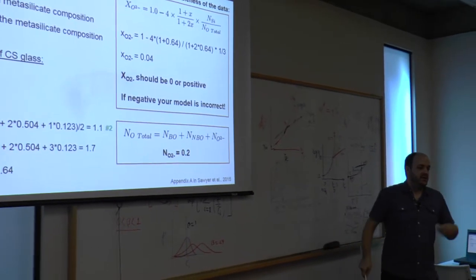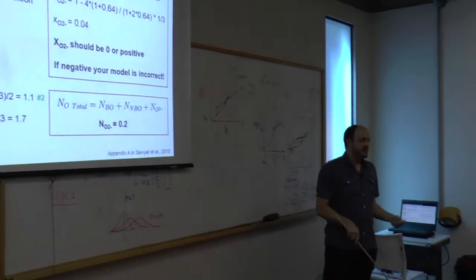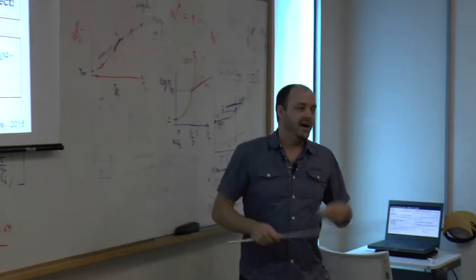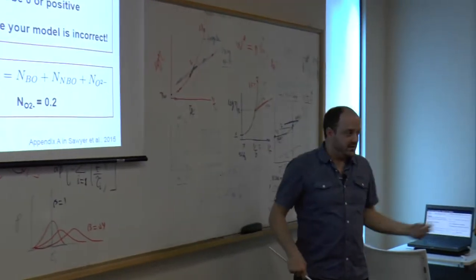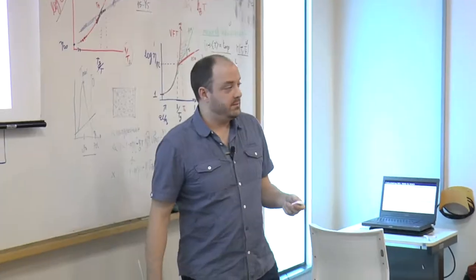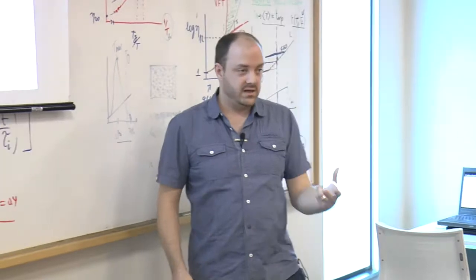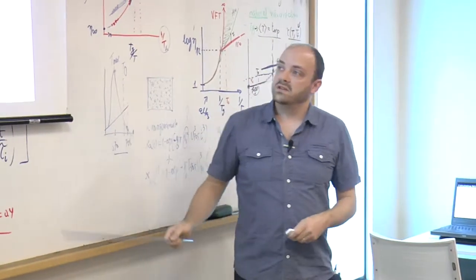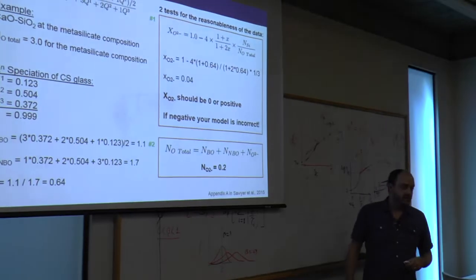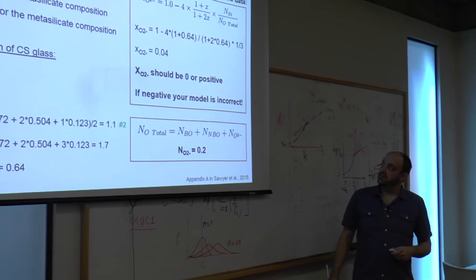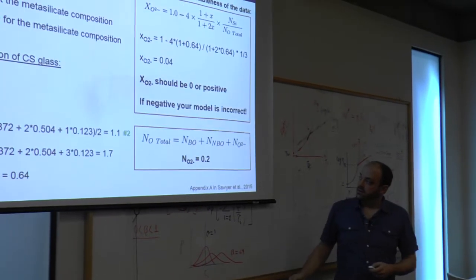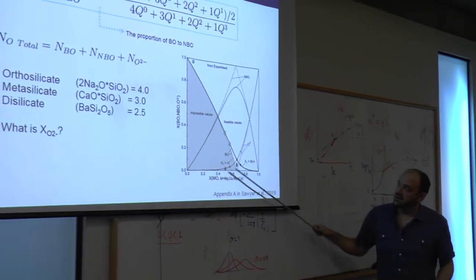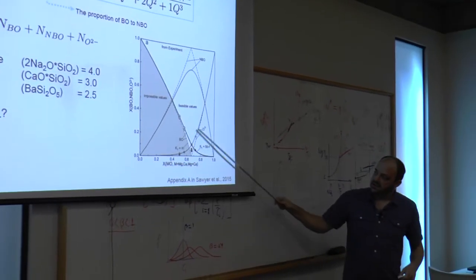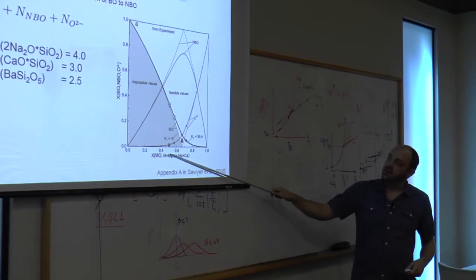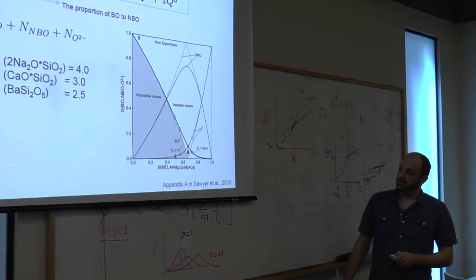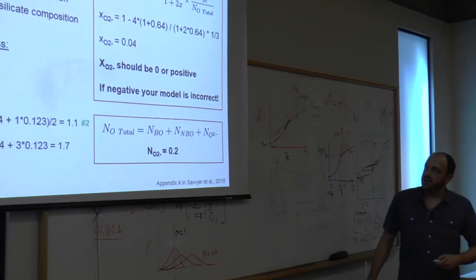And you'll see in some papers, they recognize that they got too much bridging or non-bridging oxygen, and they made a little correction, or they said, oh, we made this assumption. And then they changed their model to actually fit. So when you're fitting your spectra, when you're trying to determine QN species, and when you're reading a paper to evaluate whether that composition you're talking about actually has a reasonable model, you should use their QN speciation value and calculate these two things to see if you get a non-negative value. Then you can look at a diagram like this, and you can make it for any composition and see, do I have actually very low proportion of non-network oxygen? So those are two good tests as far as I'm concerned.